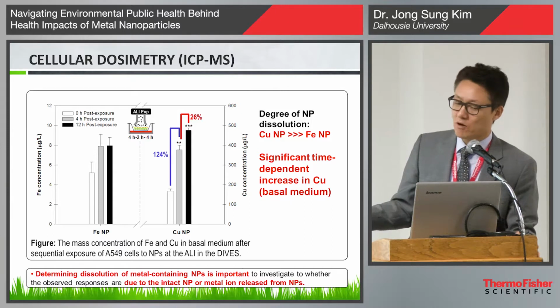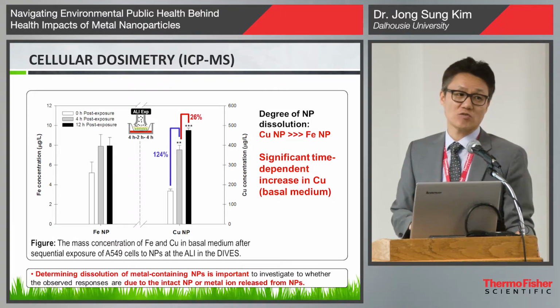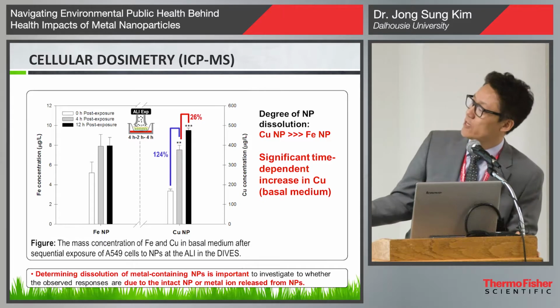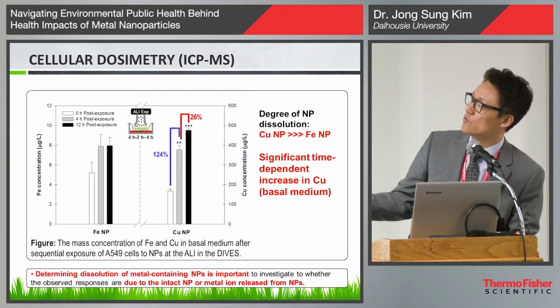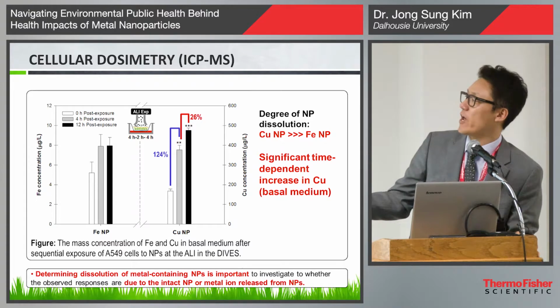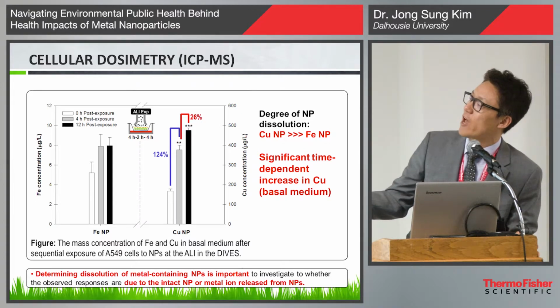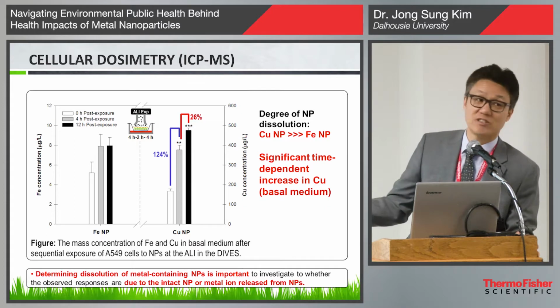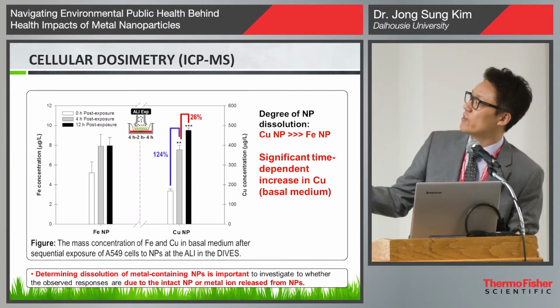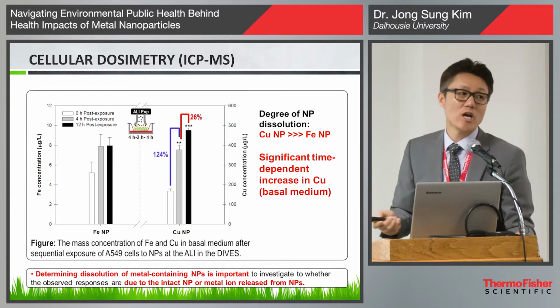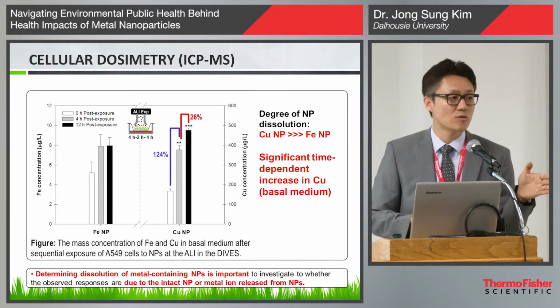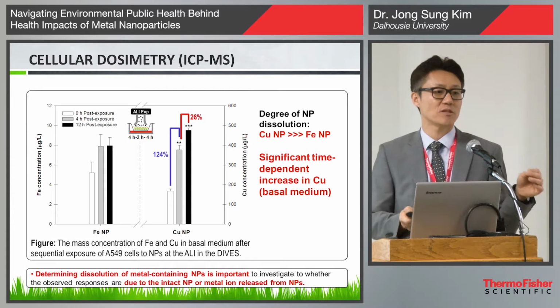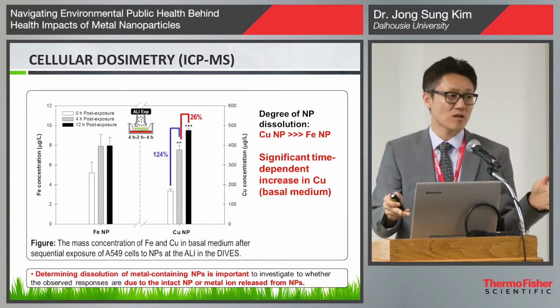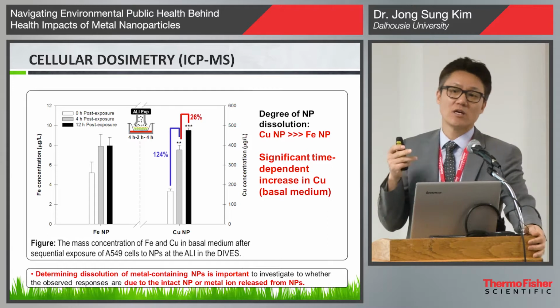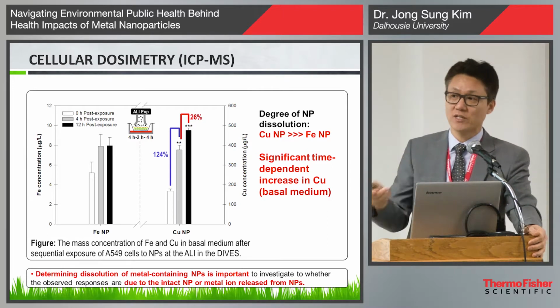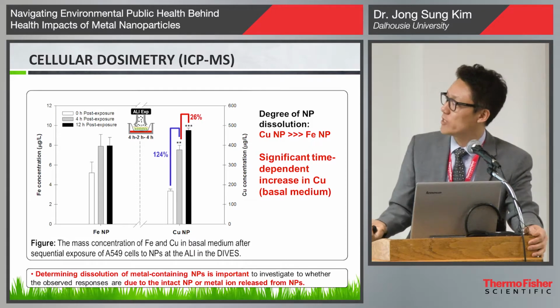When you compare directly the metal ion concentration in the media between copper and iron nanoparticles, you can see iron is only 5 or 10, below 10 micrograms per liter. So the scale is completely different here. In the copper case, you can see 500 micrograms per liter of copper. So even though you do the same delivery of nanoparticles, the same size of particle, but different composition, on the same cells, you can see the copper cases easily dissolve and release copper ions into the media.